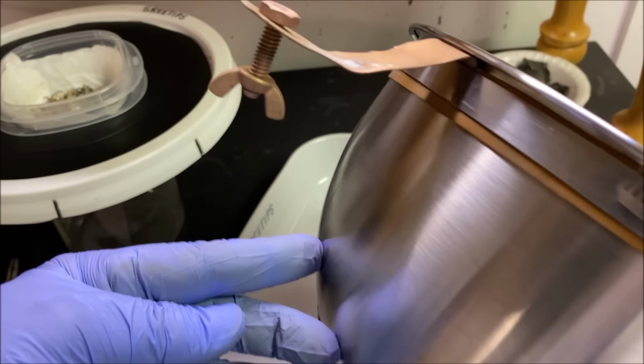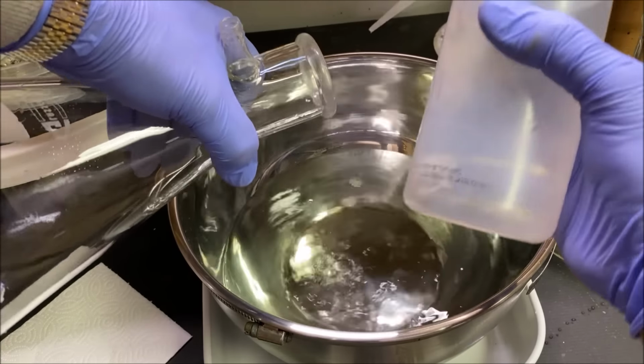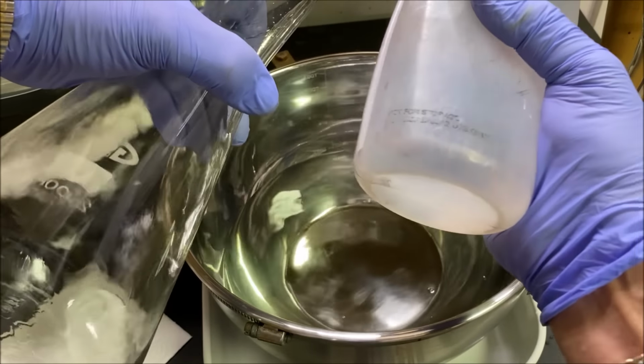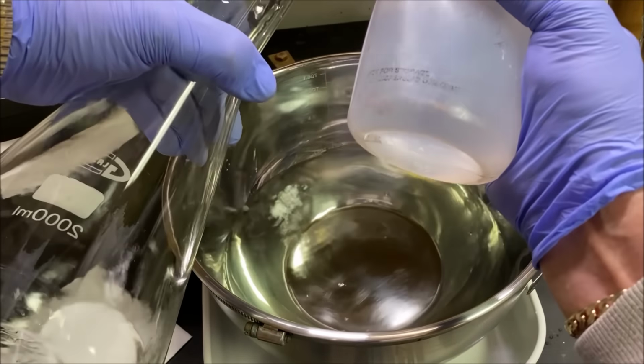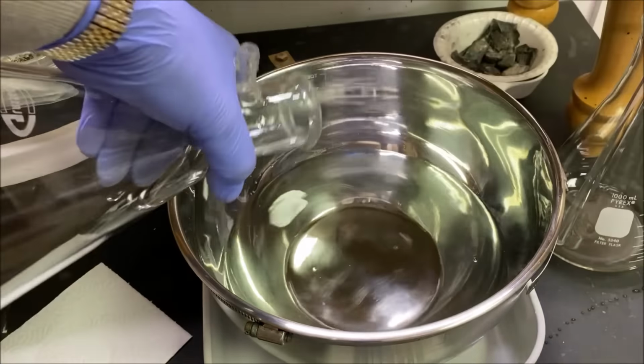Now we're going to add the electrolyte. This is 1,000 grams of pure silver dissolved in minimal nitric acid, and all the nitric acid has been consumed out of here. You don't want a whole bunch of excess nitric in this electrolyte, because then it could start reacting with the silver as it plates out or deposits on a cathode, creating some fumes. So we get as much of the nitric out of here as possible when we're making this stuff.